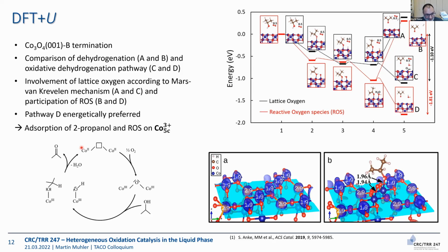That would be the catalytic cycle now, completely. That is the starting point, the 2 cobalt 3 plus oxygen, 2-propanol adsorbing, forming the propoxide species, an OH group. That means we first break the OH bond, then we break the CH bond. We release acetone, we have the reduced active site, the oxygen vacancy, and that has to be refilled and reoxidized. Rosica Pencheva made a more or less thermodynamic analysis. She was looking for the most favored pathway, and that would be the pathway down here, the red one, pathway D, where she says, okay, according to this thermodynamic consideration, it's actually the Langmuir-Hinshelwood mechanism that is energetically more favorable than the Mars-van Krevelen mechanism, where you end up with an oxygen vacancy.